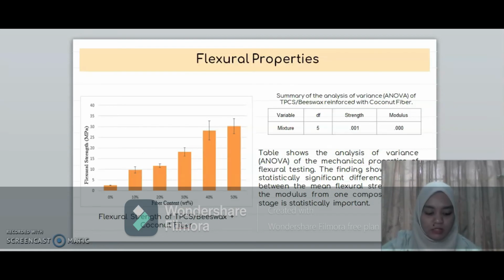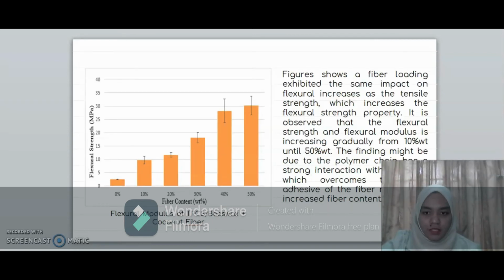For flexural properties, we can see that in general, with tensile testing, the effect of flexural testing shows a similar pattern to the tensile properties. It can be observed that the flexural strength and flexural modulus increase gradually from 10% of fiber to 50% of fiber. The finding might be due to the polymer chain having a strong interaction with the fiber, which overcomes the weak adhesion of the fiber matrix as the fiber content increases.